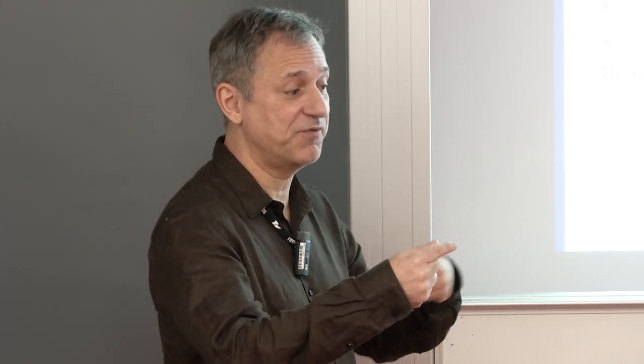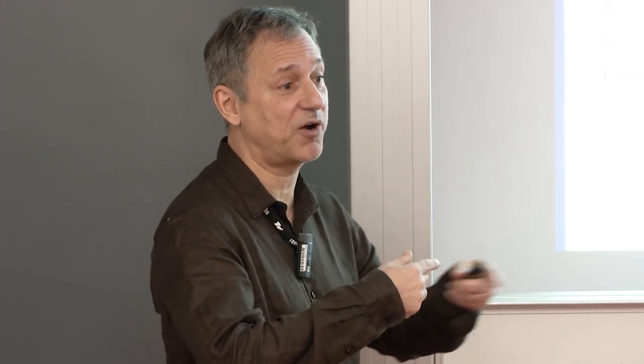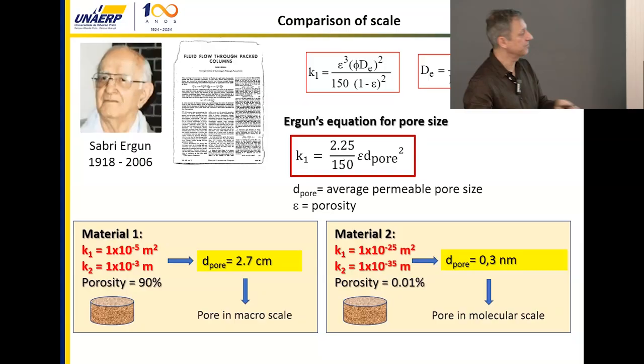For example, for the same set of material, like a concrete paste or cement paste, every time you have a change, for example carbonation or a change in the water-cement ratio, you measure permeability, measure porosity, and calculate the pore size. And you see if the pore size is increasing or decreasing, and you see what you want to decrease or increase. So you have a very good clue to where you should go in processing.